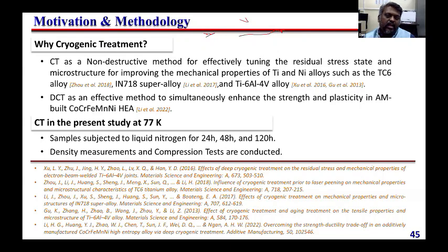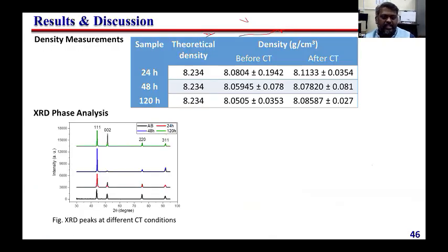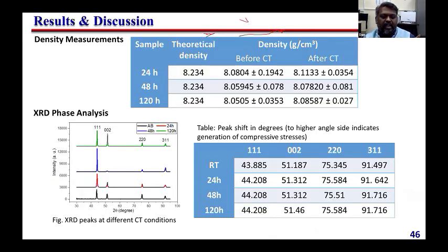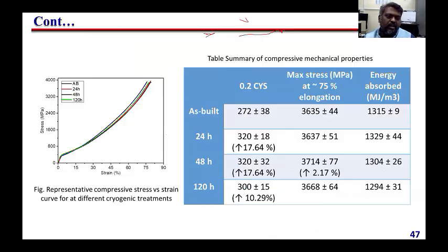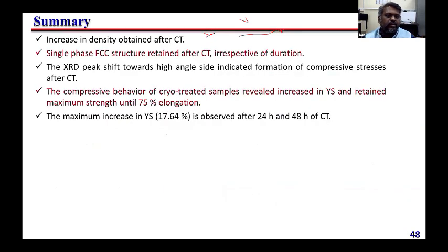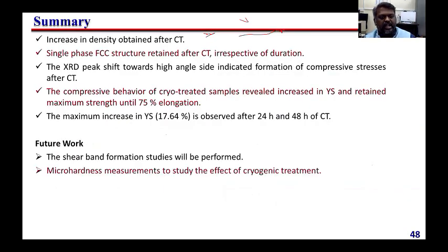So when we treat at cryogenic temperature, usually this also will induce a residual stress, and then you can increase the properties. So in that way, we did different hours of this cryogenic treatment, and we tried to see the properties, but we are not seeing much difference. But at least a 20% enhancement in the yield strength, that's what we could see, but there is not much difference in the energy absorbed or elongation. Okay, so that's what we understood from this cryogenic study.